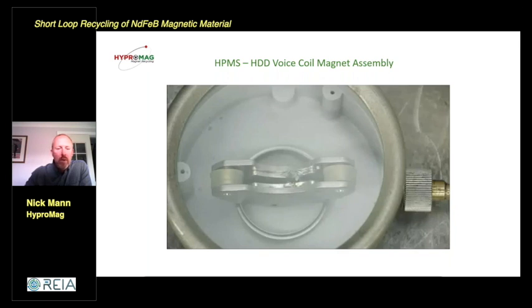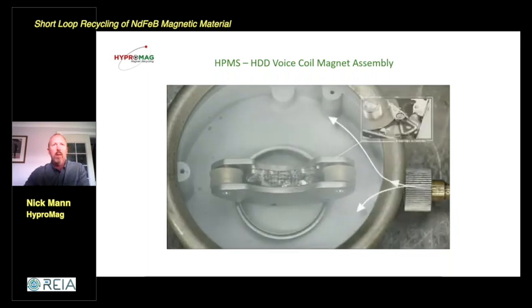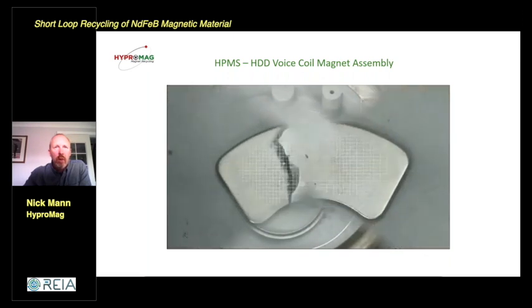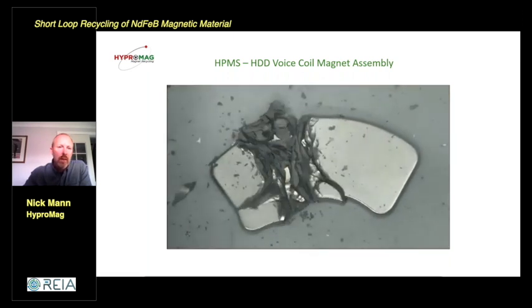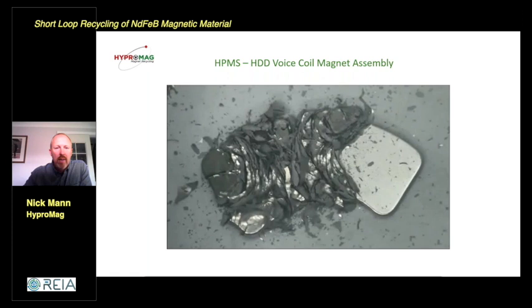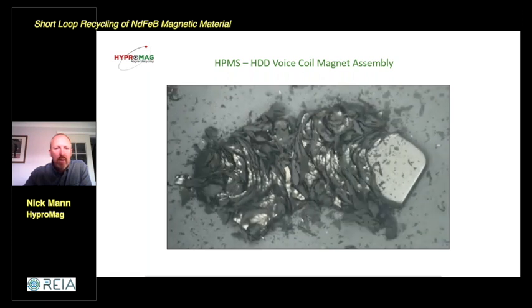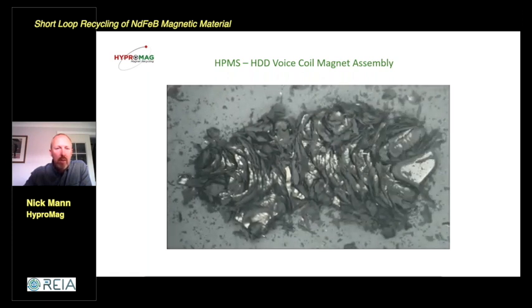So there's two important things with this reaction. It causes a volume increase, which causes the magnet to fall apart further. And it also demagnetizes the powder. So if I show you what happens, you can see the reaction propagating through. And if we show you just the magnet itself, you can see that reaction propagating through the magnet as the grains split apart and the coating cracks.